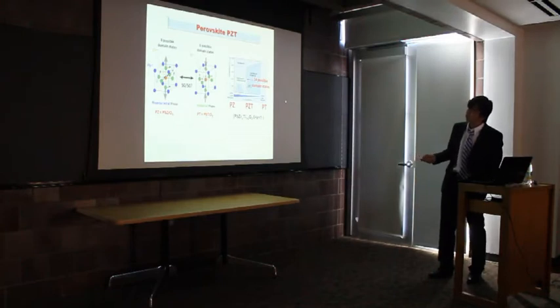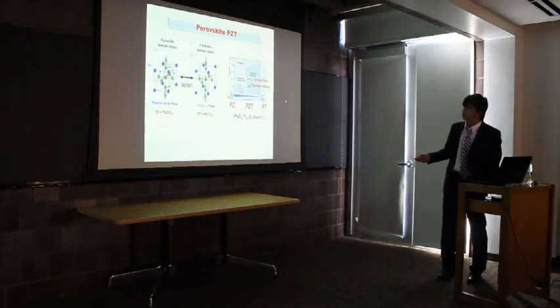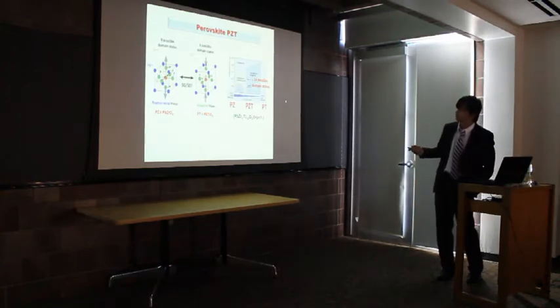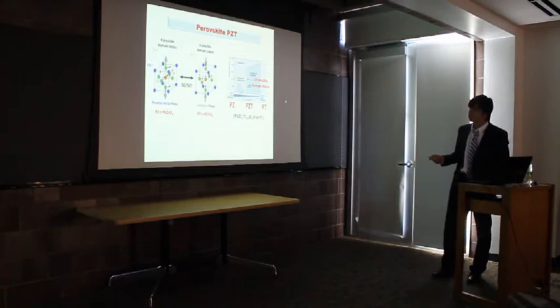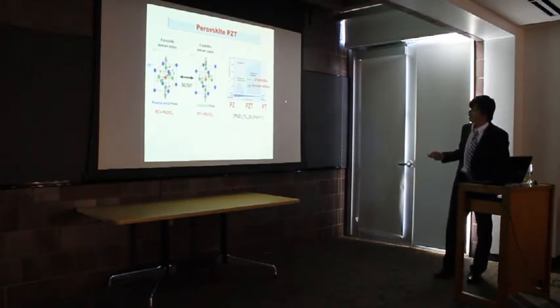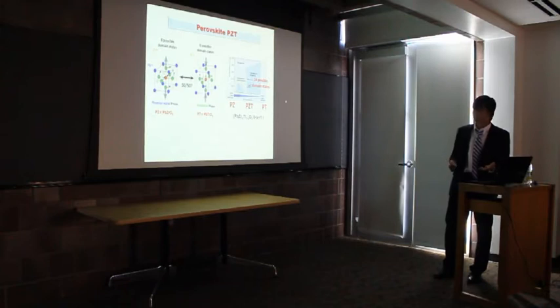For example, if you're looking at PZ, which stands for lead zirconate, because of the rhombohedral crystal structure of PZ, under deformation it has a total of 8 possible orientations to polarize towards the 8 corners of this crystal. And that's why the crystal has 8 possible domain states under deformation. Similar to PZ, PT has a total of 6 possible domain states. When you mix them together in 50-50 percentage, you make the material confused. And interestingly, the composite material PZT lying at this morphotropic phase boundary has a total of 14 possible domain states. And that explains why the material has an enhancement in D33.